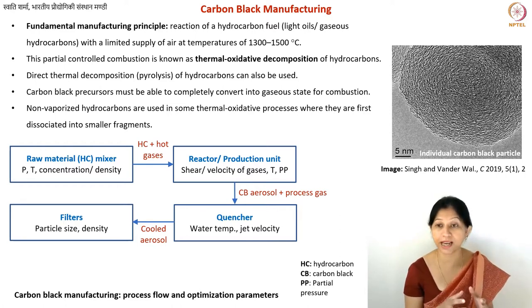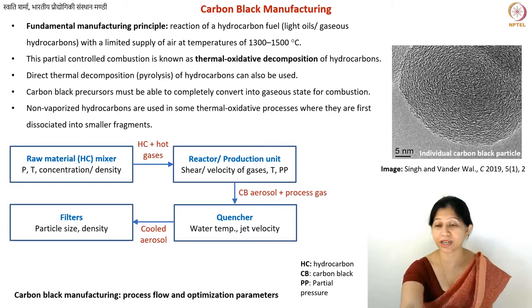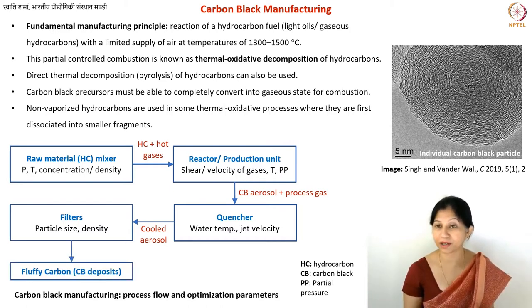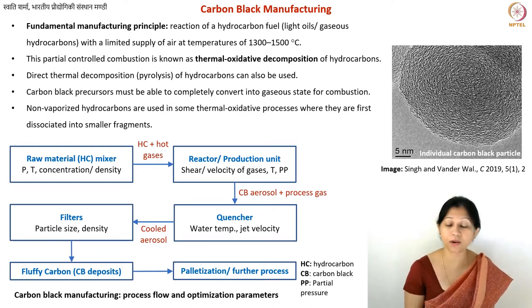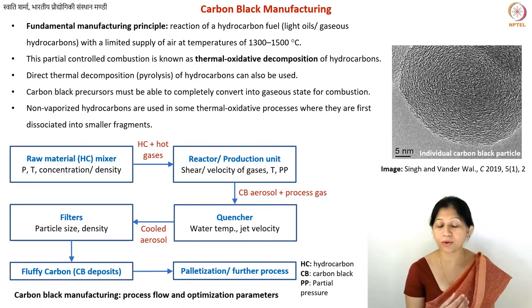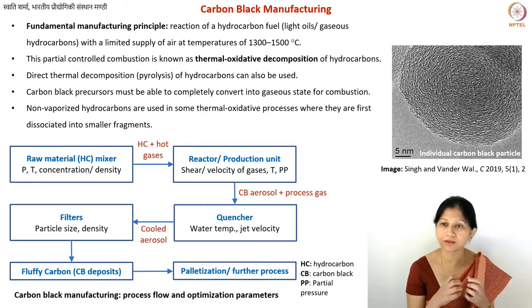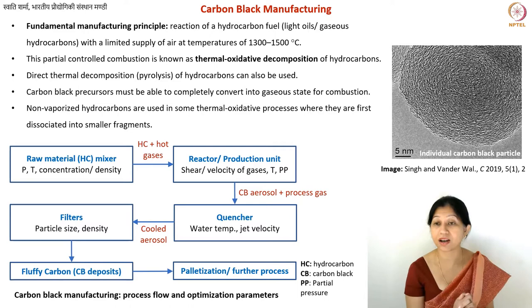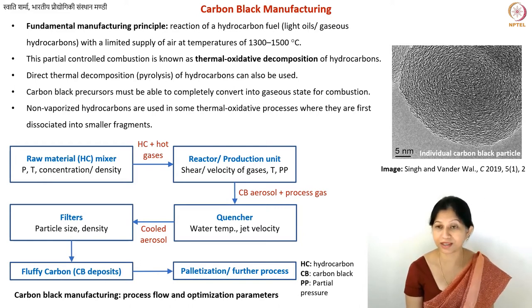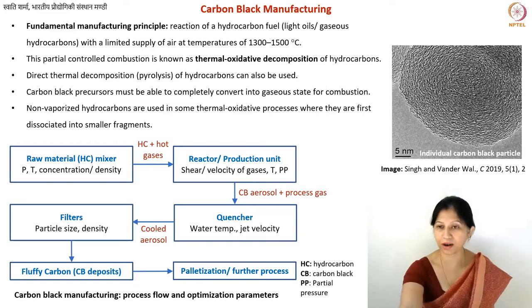In the filters, you obtain a fluffy carbon material — a fluffy sponge-like carbon deposit, also called fluffy carbon industrially. This is essentially your carbon black. If you want to sell it as pellets, you perform palletization — dry or wet. You can also perform further processes, such as oxidation, which lowers density. Some oxygen will consume carbon particles, and in some cases you can even get hollow particles with much lower density. This depends on the requirements for the final product.